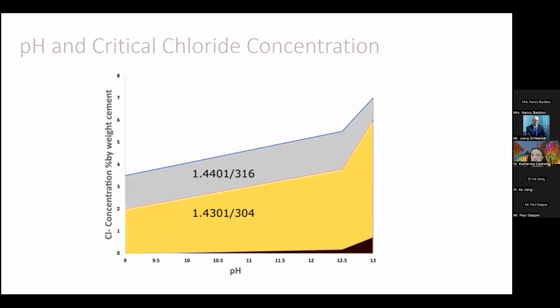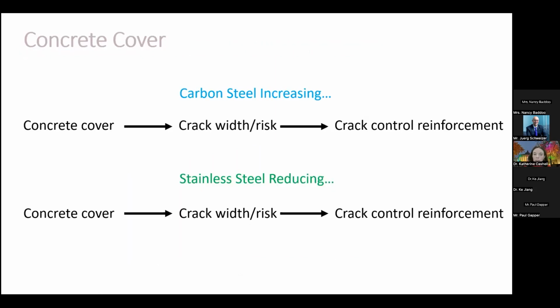Again, taking a look at that critical chloride concentration. Here we have 316 on the top, and we can see that for the high pH values, which would be appropriate for an in-concrete situation, we get a very high critical chloride concentration value for 316, a little bit lower for 304. Carbon steel is down at the bottom in black, and it is much, much lower. And where all this results is that with stainless steel, we can potentially use less concrete cover, less crack width and risks associated with crack widths, which then means less requirements for crack control.